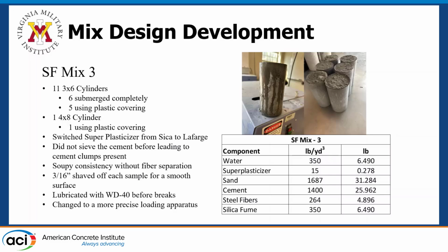Once again, this is 3/16 of an inch shaved off each sample. This was kind of our inspiring moment to be like, okay, we need to break these properly. And we switched our superplasticizer from Sika to Lafarge because we actually found that with Sika, you need a lot more. We were able to reduce our superplasticizer and our water by half using Lafarge.